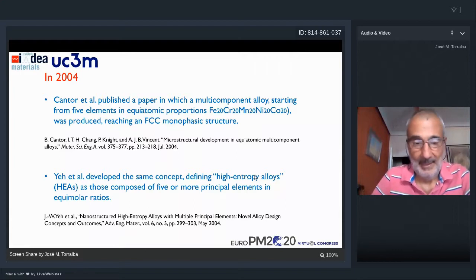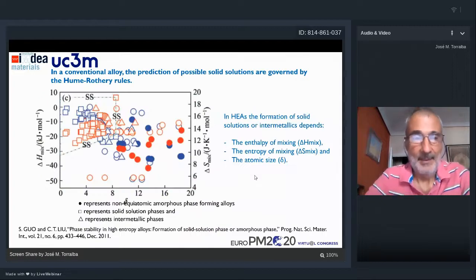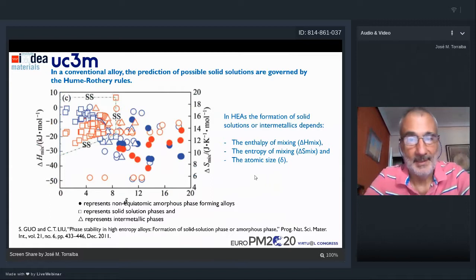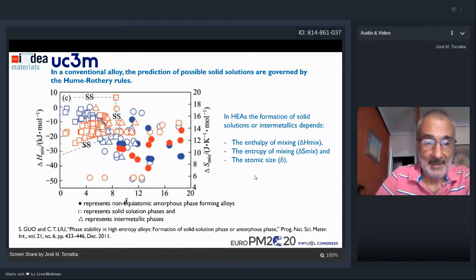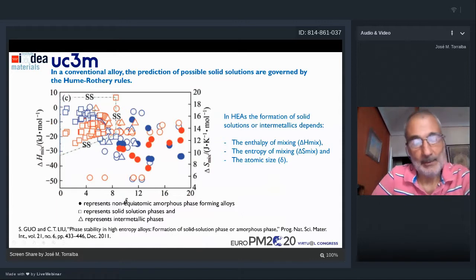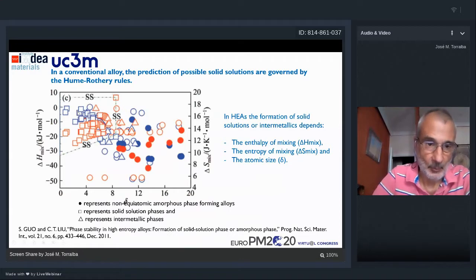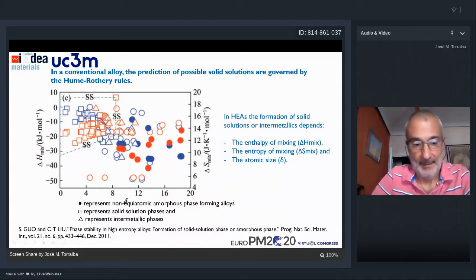So what they demonstrate is that in these alloys, the conventional Hume-Rothery rules in order to predict the possible solid solutions are a completely different matter. In that case, if you have a high entropy of mixing and a reduced atomic size difference, you can be in this area of the graph in which you can expect a solid solution. Later, I will explain a little bit more about these conditions, but if you fulfill these two conditions, a high entropy of mixing and a low atomic size difference, you can be in this square in which you can have only one single phase.